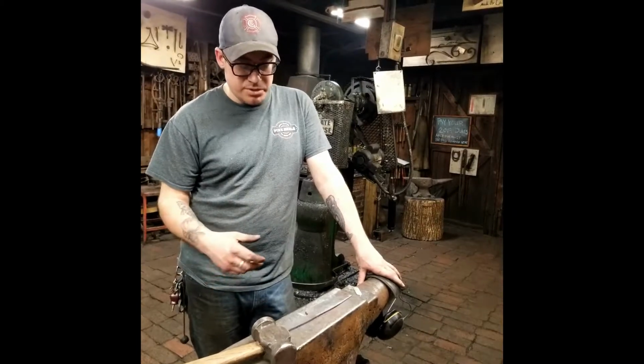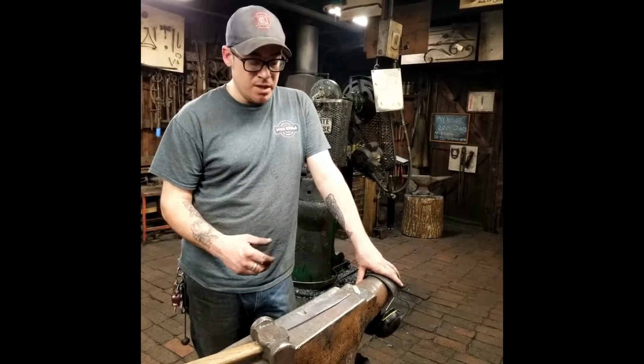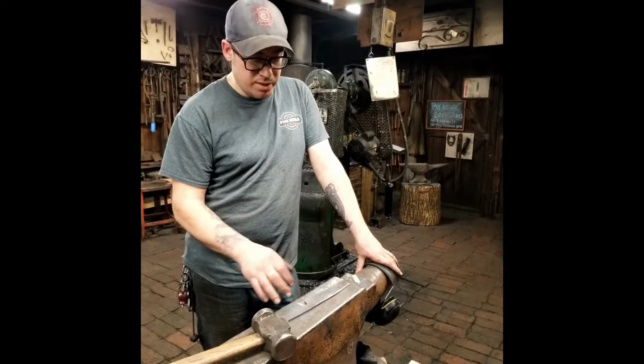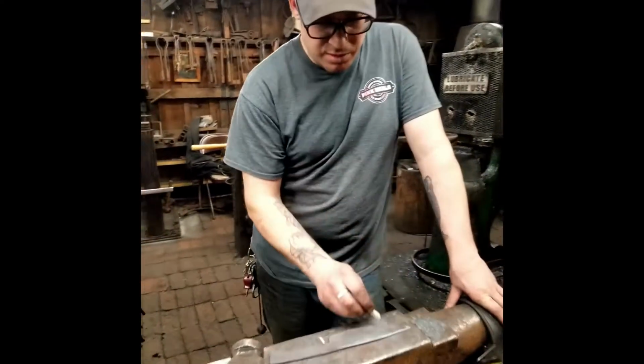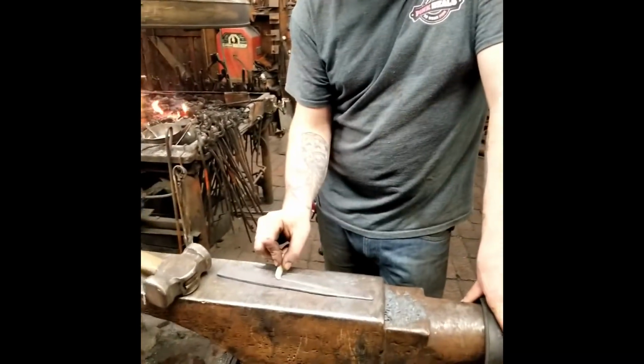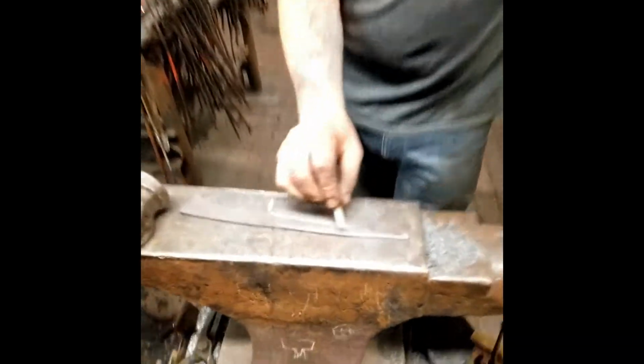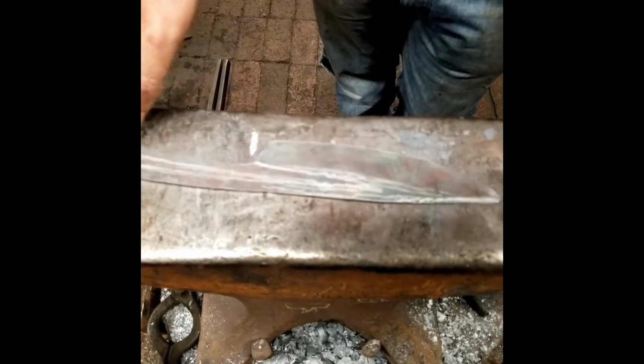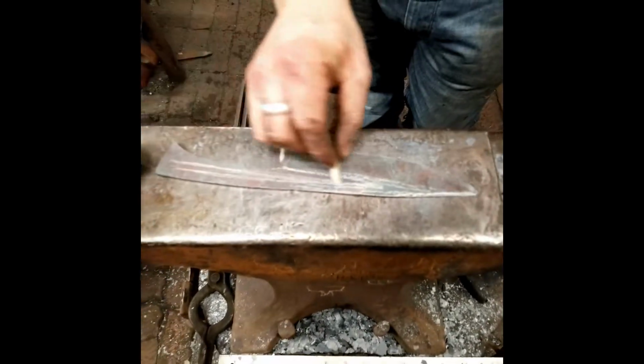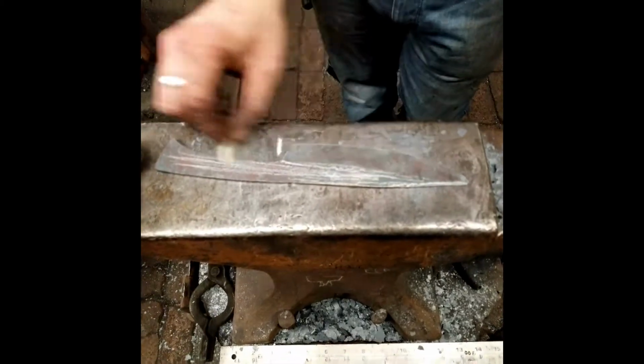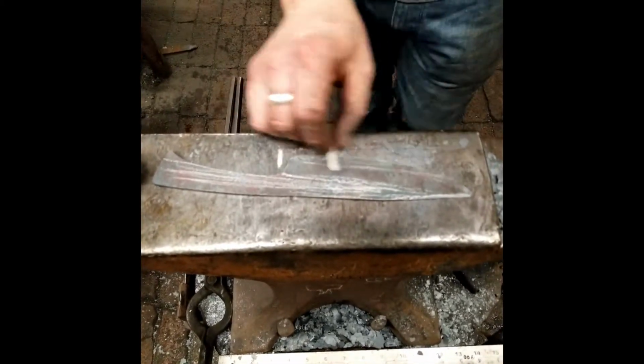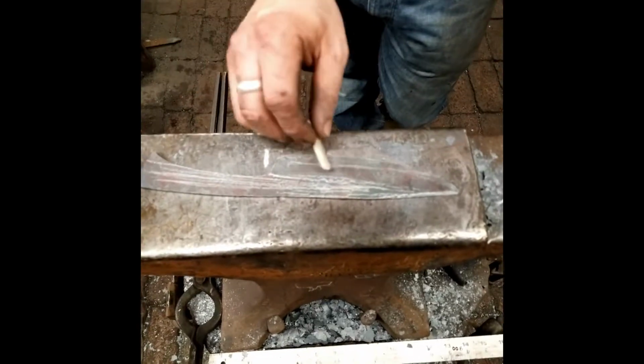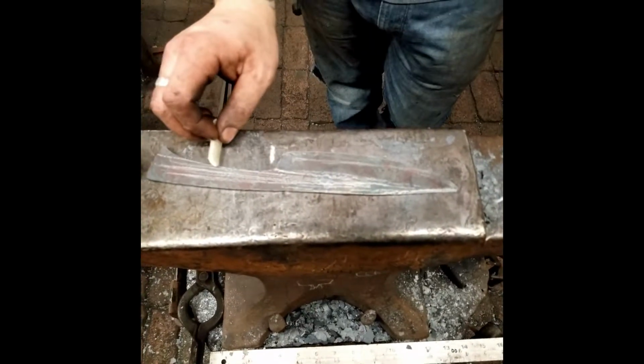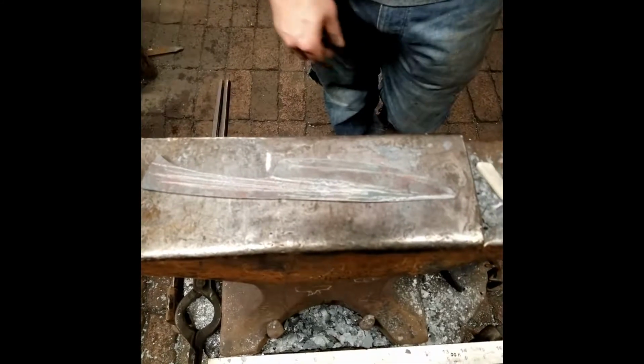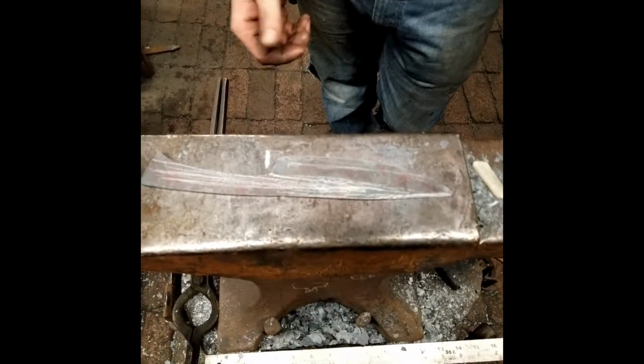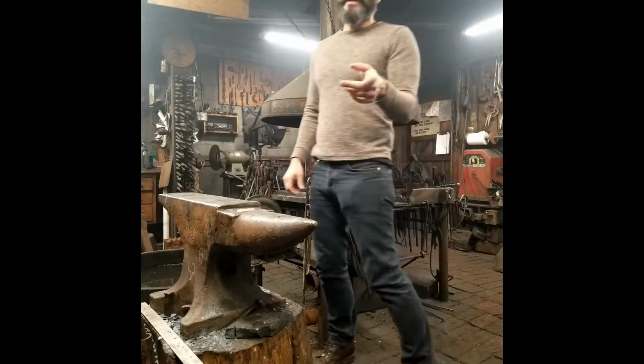If it's a hunting knife, something that's going to be under a lot of heavier stress, I'll temper it anyway, but then I will put the knife back in water about this much, and then torch all of this area to draw out. And that's a draw temper. So this is all soft, and this still maintains your original temper. So if you bent this knife 90 degrees, it won't snap. So it's better for chopping, especially for hunting knives.